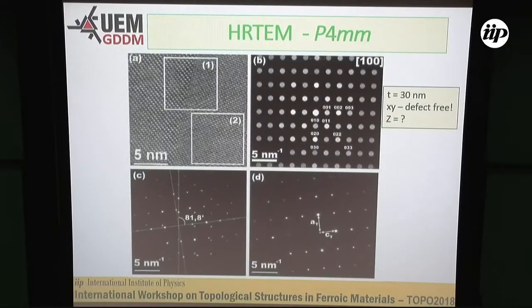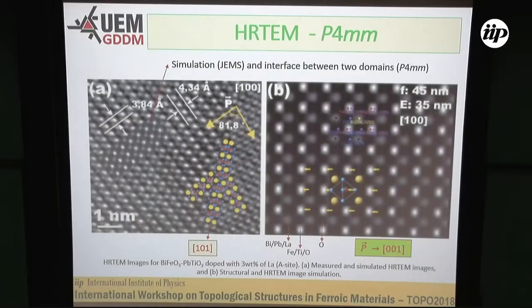It's also important that this result shows us that this sample in this area is almost defect-free when you see the XY plane of our sample. And for the Z, we don't know if it's defect-free, but the simulations give us that probably the thickness of this sample in this region is about 30 nanometers. Very good behavior for this 30 nanometers. Amplifying that region for the simulation, you see that this simulated image matches completely with the structure. And here, the interface is in this direction, 101 of the tetragonal unit cell. And these are the lattice parameters determined by the software for the A and C lattice parameters in this sample.